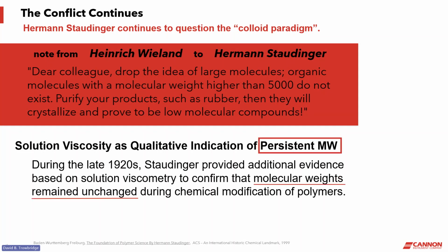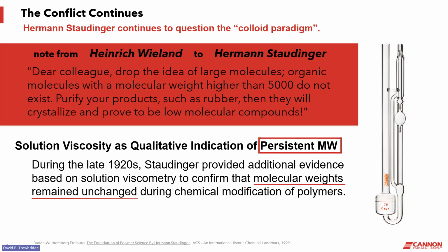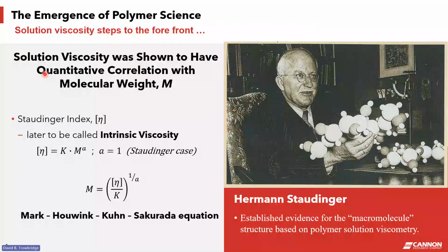He made measurements using capillary viscometers. I'll show an image of it here in a minute, but the underlying point of his first early experiments was that he got a persistent molecular weight based on consistently high solution viscosities, even after chemical modification. So this viscometer is the kind that he would have used. It's made out of glass, and it has several dimensions that are important that I'll describe in a later slide. But the takeaway idea that he presented is that solution viscosity was directly related to molecular weight. In fact, he carried this notion to a further level where he actually made a statement saying that the solution viscosity was quantitatively correlated to the molecular weight.